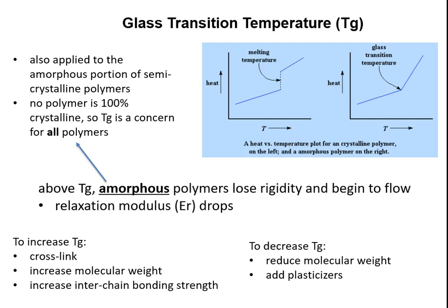If we looked at glass transition with the same kind of scan in temperature and then measuring heat flow, we wouldn't get a jump in the line, but we'd get a slope change. And this is called a second order thermodynamic transition. So we can actually look at plots of heat flow as a function of temperature change with a method called differential scanning calorimetry. And that's one of the ways that we can measure Tg for a given polymer and then use that information to understand at what temperature we're going to get these dramatic changes in mechanical properties and design around them.